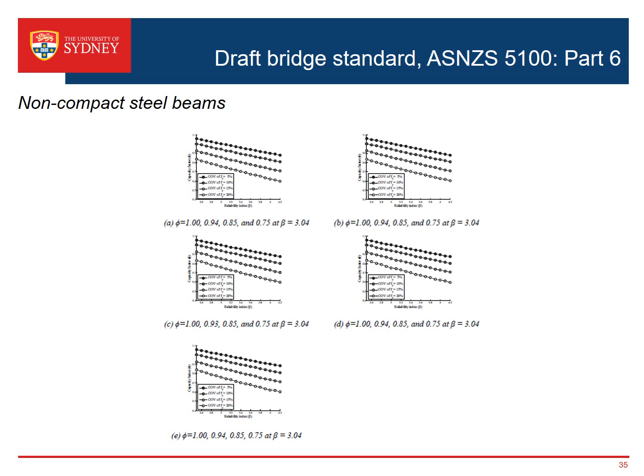And now if you look at the joint structural standard, which I think most European codes have been calibrated to, coefficient of variation of yield stress is about 7%. We don't actually stipulate in the Australian New Zealand standards what that variation should be. My colleagues and I think if we set it to not be greater than 10%, and you can see by the results that we have here, by doing that we would maintain our reliability index of 3 and above, and we would also maintain a capacity factor of 0.9 and above.